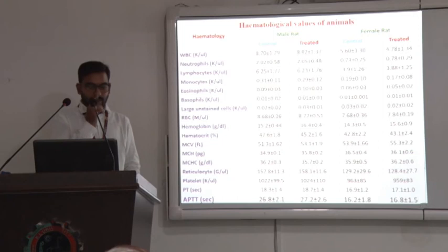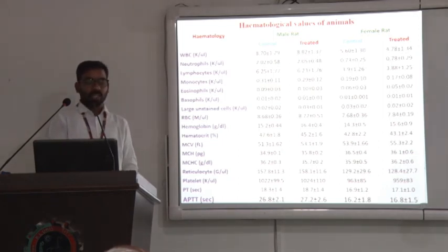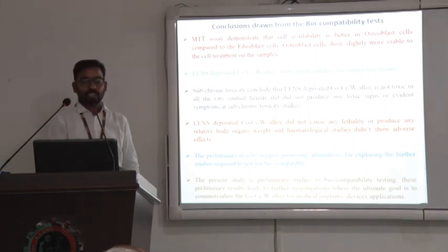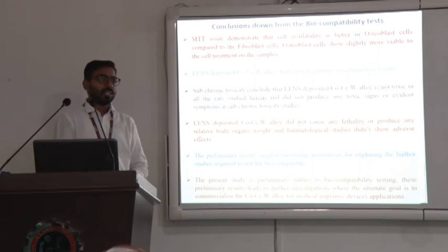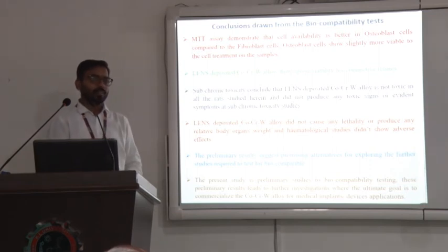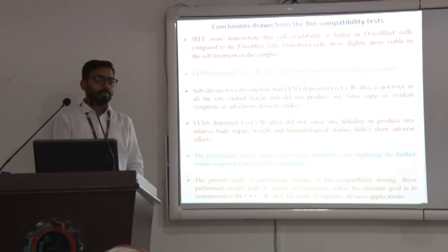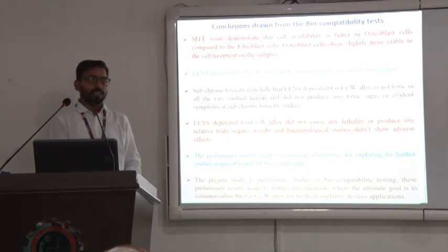It is further observed with the hematological values, on the blood and serum of rats, for both control and treated. The treated values are compared with the control values. Here also we can find no significant difference. We can conclude that this subchronic toxicity does not release any toxin to the living cells of the rat, and partially we can conclude that these laser deposited samples are suitable for medical implants.